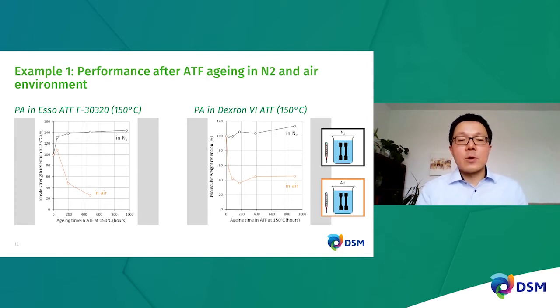The same story for polyamide in Dexron VI ATF at 150 degrees Celsius in the right-hand side figure. In this case, the molecular weight retention is plotted as a function of aging time. In nitrogen, you don't see any decrease in molar mass, whereas in air environment, you see that dramatic decrease, especially in the first few 100 hours. So here, this is really highlighting the importance of ambient atmosphere during aging.